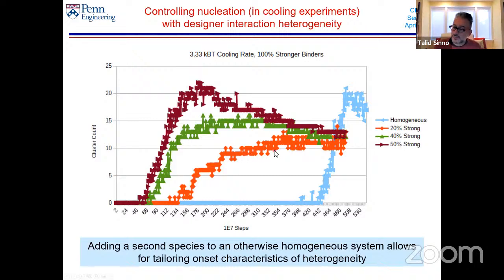And so I can control my crystallization outcome by seasoning, if you will. And in this case, I don't have a Gaussian distribution of interactions. I'm literally just using a second component. It's like adding a little bit of hot pepper to the system, but not too much, just to spike it.